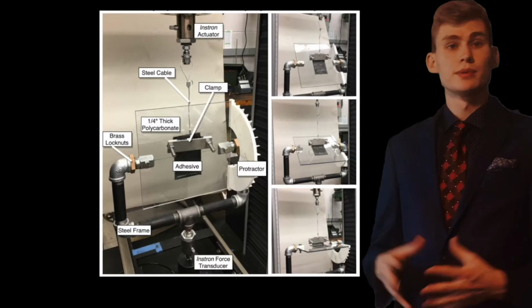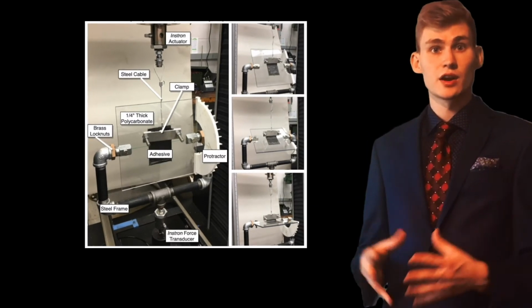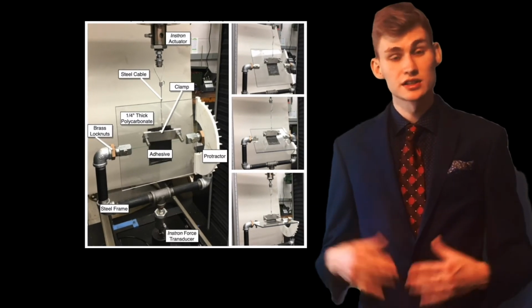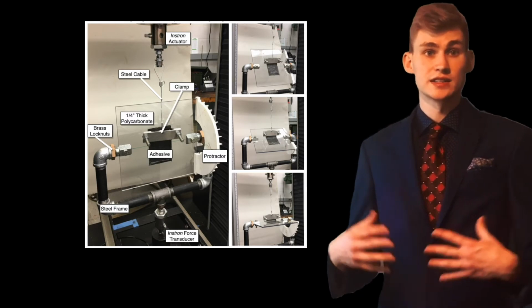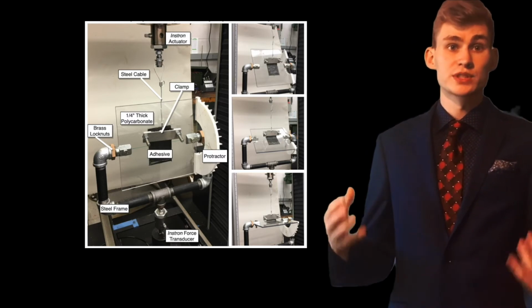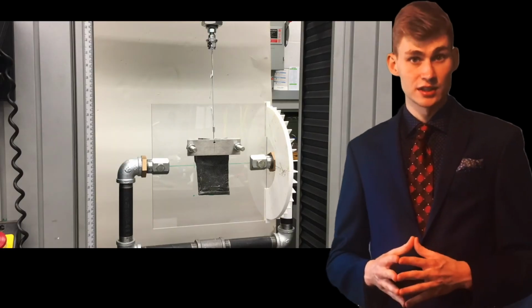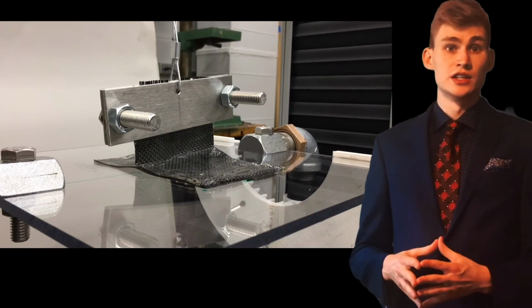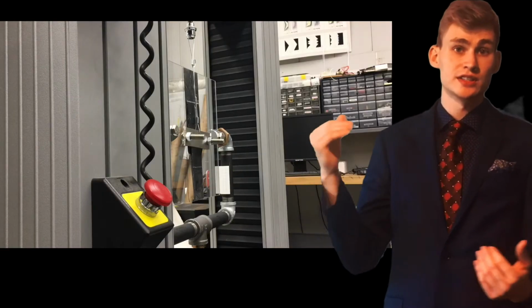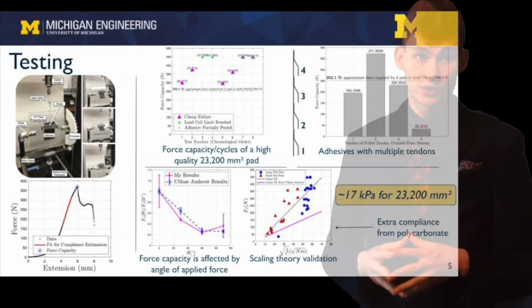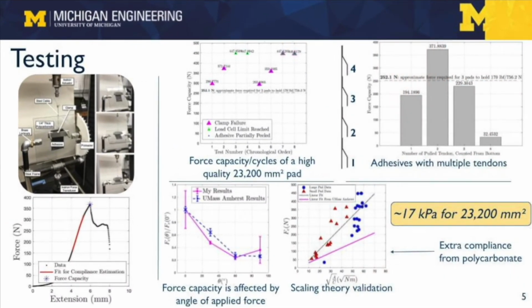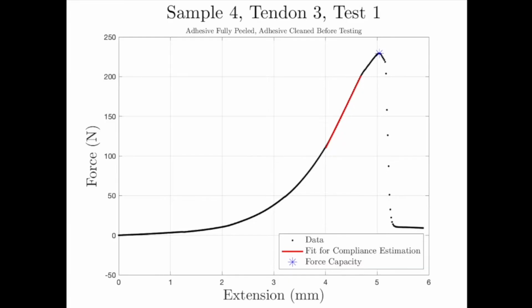Using a custom built testing setup with a polycarbonate plate as the adherent surface that is allowed to rotate about an axis so that I could test different loading angles, I performed simple force versus extension tests on the adhesive, where the Instron instrument increases the displacement on its anchor while measuring the resulting force using a load cell. The raw data from these tests all revealed two things: the force capacity, which is the maximum force measured before failure, and the compliance, which is the reciprocal of the slope of the linear region, i.e. the reciprocal of the stiffness.